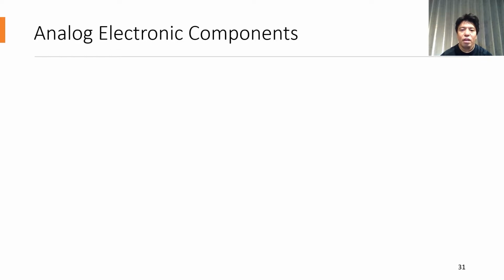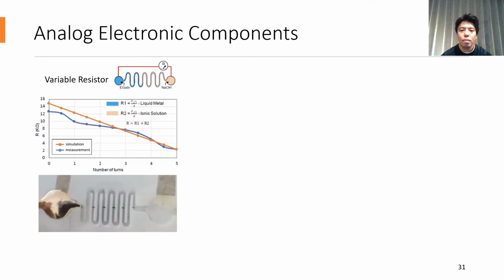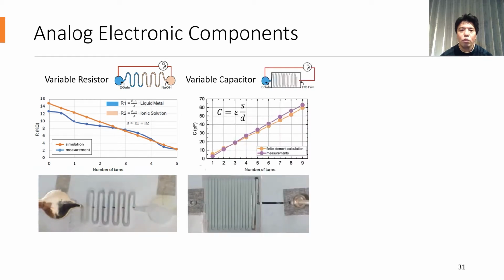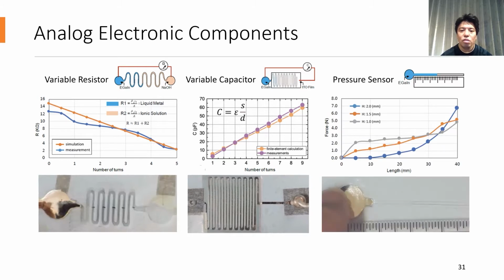Analog electrical components are another application. We can create a variable resistor by infusing different volumes of two conductive liquids. As the law of resistivity simulates, resistance decreases proportionally to the volume of high conductive liquid metal. We can also design a variable capacitor by controlling liquid metal flow between ITO electrodes. We found a linear increase of the capacitance with respect to liquid metal area, as the equation for a parallel plate capacitor predicts. We can also use force-sensitive liquid deformation as a pressure sensor after calibration.